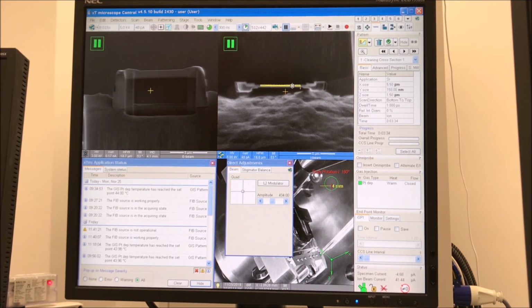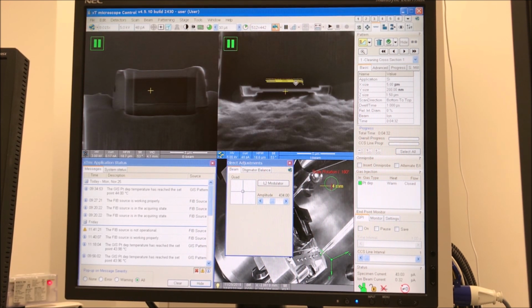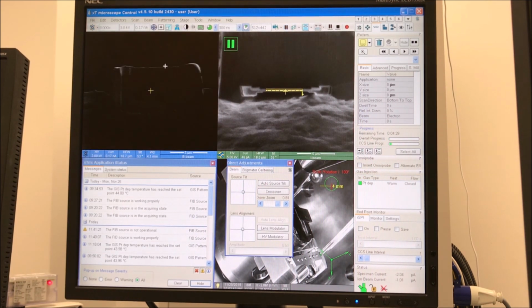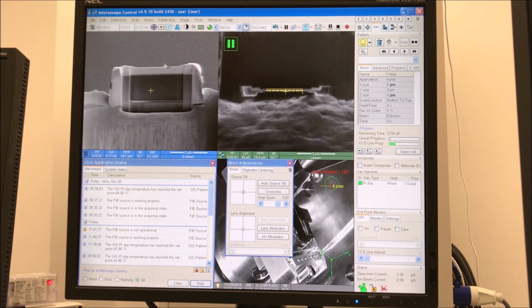And one thing you may notice when you drop the ion beam voltage is that there's some drift in the image as a result of the voltage change, and that takes a little bit of time to settle down. And so I actually made a little bit of a mistake here in that I didn't wait for that to settle before I started doing my milling. So this step actually was a little bit more aggressive than I would have liked, but it still ends up with a usable sample. But you'll see I actually stopped this pattern prematurely to prevent overmilling of this side of the lamella.